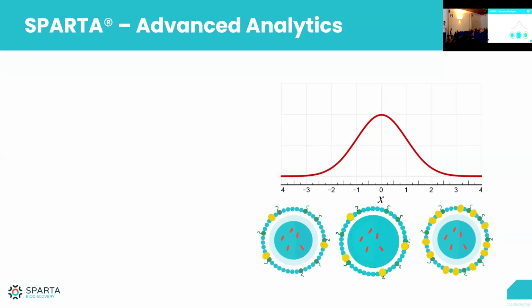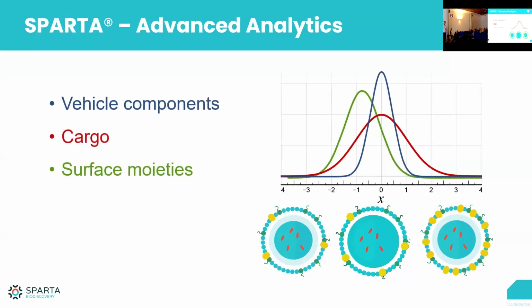What we say is that for every kind of component in your particle, there is a distribution. We can look at different vehicle components, cargo, or surface moieties, and they all might have different distributions as well. So it doesn't mean that there's only one type of distribution inside your formulation. It could be very homogeneous in the amount of ionizable lipid in your LNP, but very inhomogeneous in terms of the targeting ligands. So this is really where we need much more advanced chemical analysis techniques that can actually profile all the different components you're actually interested in for your type of formulation.